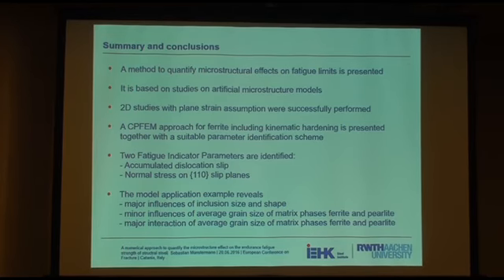To sum up, I've presented a method to quantify the microstructural effects on the fatigue limits. This one is based on simulations with artificial microstructure models. They were done in 2D with plane strain assumption. I've been speaking about the CPFEM approach that we used. I've also mentioned that 2 fatigue indicator parameters were used, and I could reveal some more or less important microstructural influence on the fatigue strength of this material.